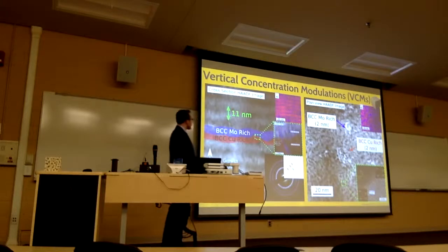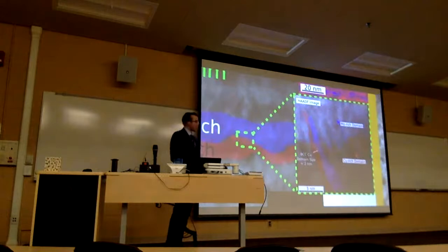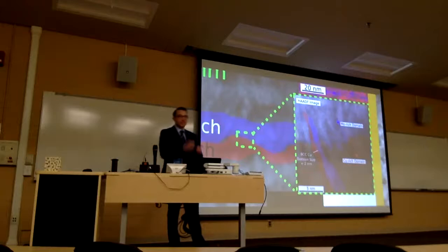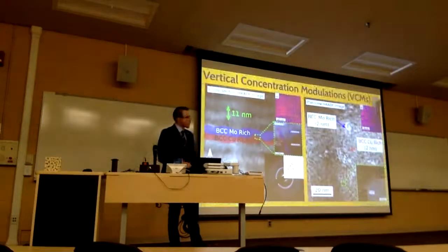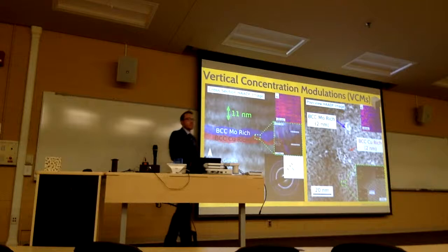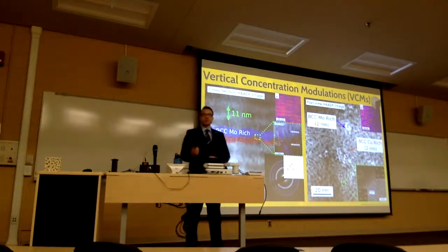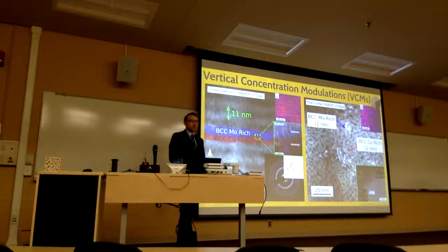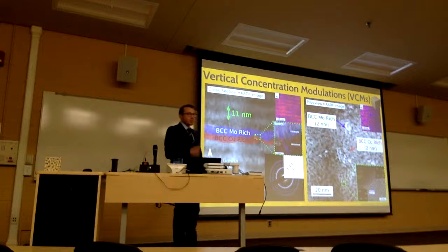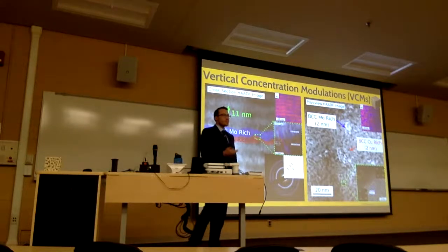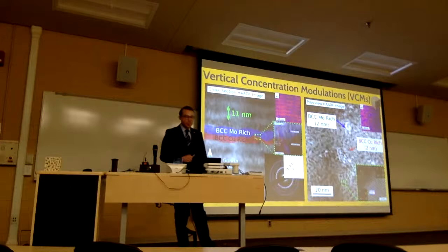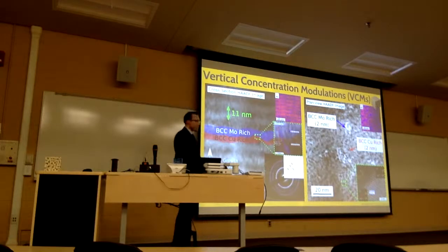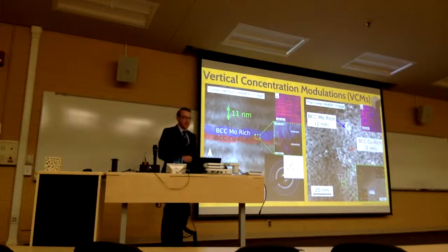If we actually look into these two domains, what you can see is that there's actual lateral character to the copper- and moly-rich domains that extend into the thickness of each of those layers. What's really interesting about this sample is that if we measure the crystallography, we only pick up frequencies from the body-centered cubic crystal structure, which is represented by moly, which is the equilibrium moly crystal structure. But if you know anything about bulk copper, the equilibrium crystal structure is actually face-centered cubic. So what we have here is actually a metastable copper layer coherent with the BCC moly-rich layer.